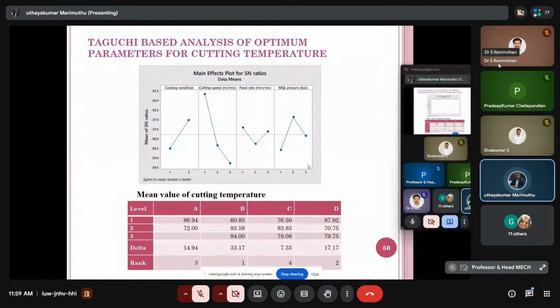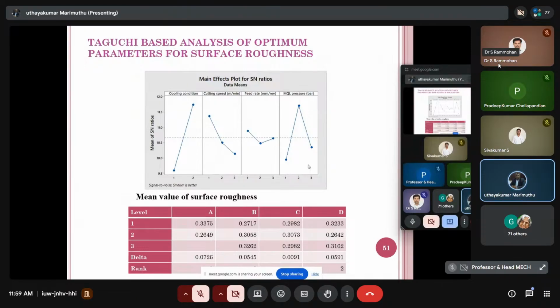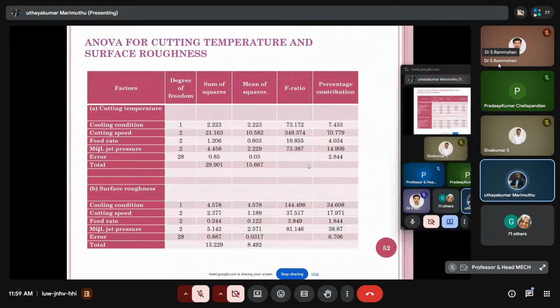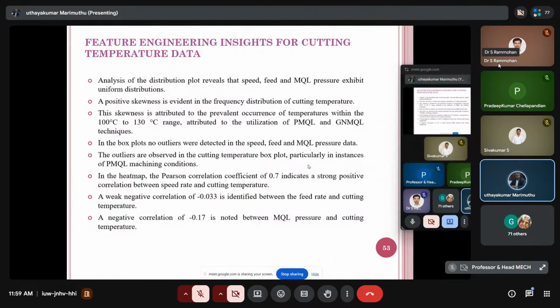So this is about the mean value, and you can see for the surface roughness, earlier it was temperature, this is surface roughness. Now for cutting temperature and surface roughness, these are the feature engineering insights for cutting temperature data. Analysis of the distribution plot reveals the speed, feed, and MQL pressure exhibit uniform distribution. A positive skewness is evident in the frequency distribution of cutting temperature. The skewness is attributed to the prevalent occurrence of temperatures within the 100 to 130 degrees centigrade range, attributed to the utilization of PMQL and GNMQL techniques.